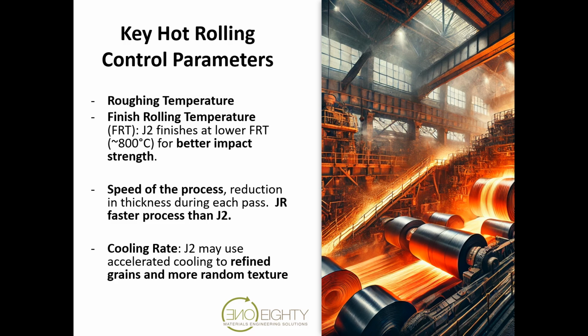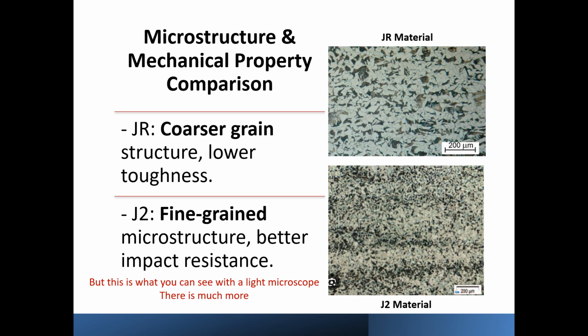The cooling rate for J2 material is also accelerated to refine the grains and to also randomize the texture. And I'll come back to what textures are. But looking under a light microscope, you can see the top image is JR material and the bottom image is typically J2 material. And you can clearly see the difference in microstructure between the two materials.